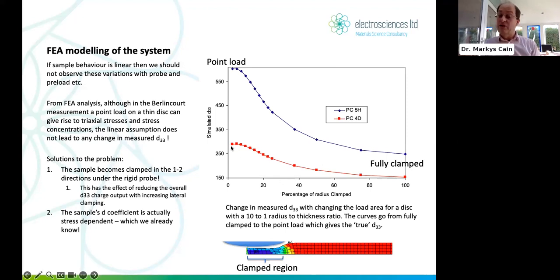When the radius of that material clamped is very small, in other words, you're using just a point contact, the stresses are high for sure, so we have a stress-induced issue, but the clamped region is very small, which means our actual simulated value is what you'd expect from the book value of D33 of these materials. But as we clamp this sample more and more using a wider and wider and flatter punch, we reduce the effective piezo coefficient all the way down here.